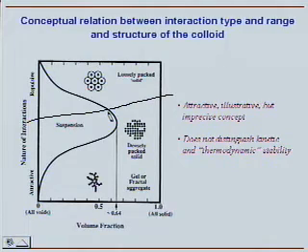Now, when you go to a very slightly repulsive interaction, you can get them to about 0.64 in volume fraction. Now, what happens even in this case where you go above 0.64 in volume fraction? The particles just get closed so tightly that they actually form some solid-like material, which can be also ordered.